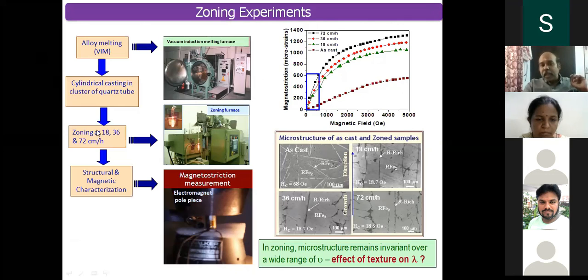What happens is, you have an induction coil here. Inside the induction coil, you keep your material and then you slowly move the coil from top to bottom. When we move the coil from top to bottom, there is a preferential growth of grains happening. And this preferential growth of grain is found to be dependent on the pulling rates, that is the rate at which I move the induction coil.